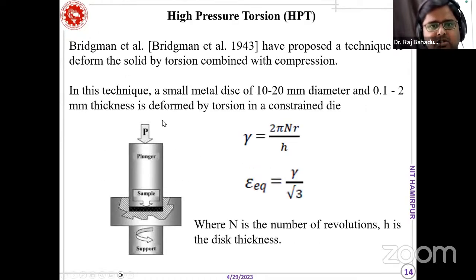So first is high pressure torsion. In that we have a very small sample, with a thickness of 0.1 to 2 millimeter only, and a diameter of 10 to 20 millimeter. Before I discuss all these techniques, the beauty of all these techniques is that the cross section of the material is not going to be changed even after very severe deformation. Like rolling, if you deform 50%, then the cross-section area will be reduced, and after some extent of rolling, you will not be able to deform the material further. So you can only impose strain in the conventional process up to some limited strain only.